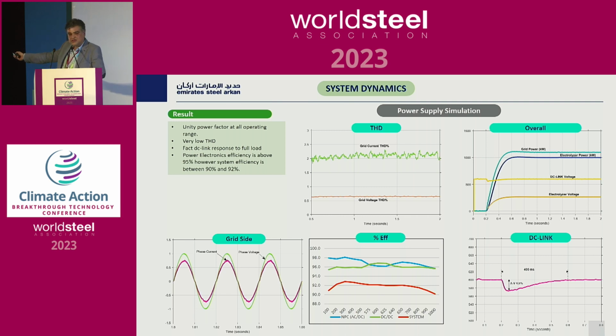This is very important, the DC link, or the voltage on the electrolyzer. We can see that when we load it suddenly, it only goes 4.5% below the nominal one, but it recovers in 400 milliseconds. It is a very, very fast response for the electrolyzer.